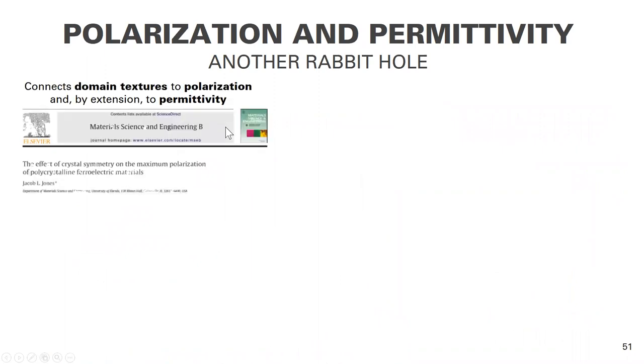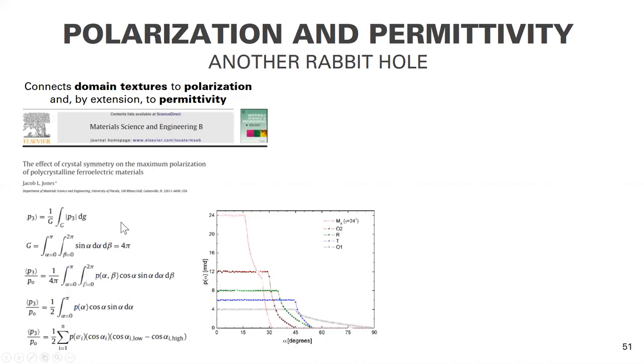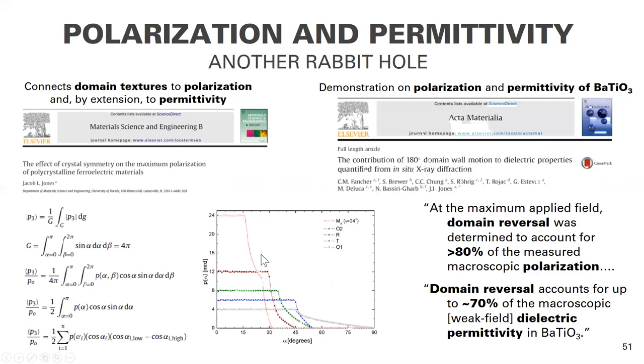All right, there's another rabbit hole we're not going to go down today, but I just want to introduce it for completeness. And that is the thought that you can connect these types of measurements of domain textures to polarization, and then by extension also to permittivity. And you can find a couple papers in the literature that describe that. These equations are outlined in this first paper on the topic. We once again did saturated poling models for the polarization textures. And then we applied it several years later to barium titanate to calculate the contribution of domain reversal to the dielectric permittivity in barium titanate, and we showed it to be about 70%.